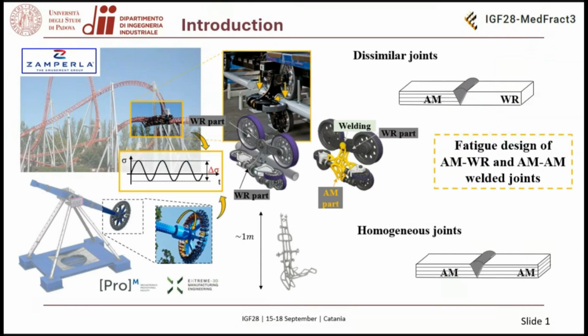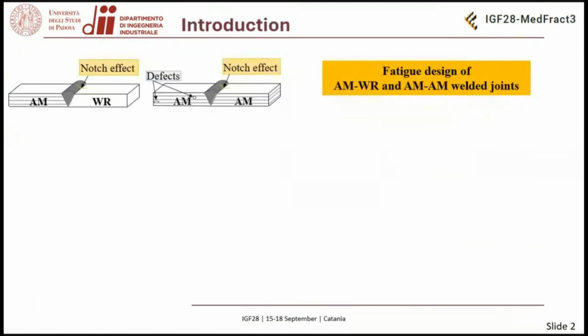But as we all know, structures like these are often subjected to cyclic loads, and this means that we need a fatigue design of these joints. But if we refer to traditionally manufactured welded joints, we know that the most critical point is represented by the weld toe due to the notch effect. In this case, where we have also an AM part, we need to take into account also the possible presence of defects due to the manufacturing process.